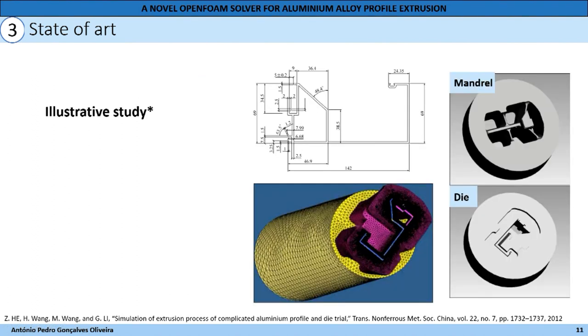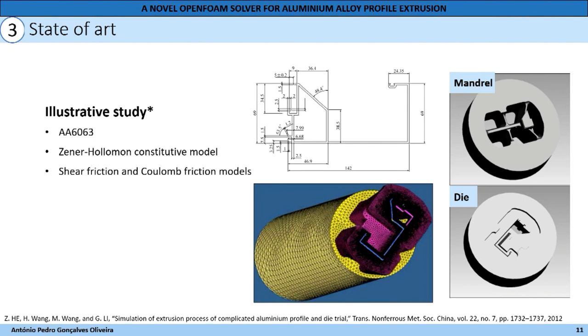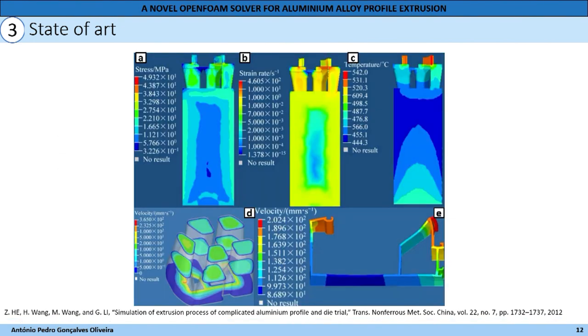There are already some studies in the aluminum alloy extrusion field. Here we can see one of those studies where the simulation of an extrusion profile is performed. The die, mandrel and CAD model are also illustrated. The material for this study is the AA6063, where the Zener-Hollomon model was selected, and also the shear friction and Coulomb friction models for the wall boundary condition. Simulation fields of stress, strain rate, temperature, and velocity solutions are shown in this picture, and they are very important for selecting process parameters.